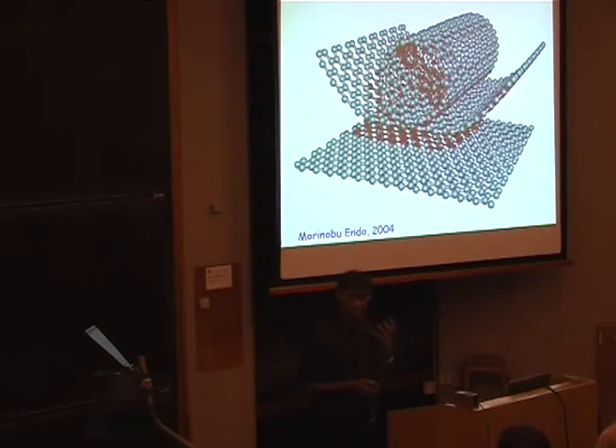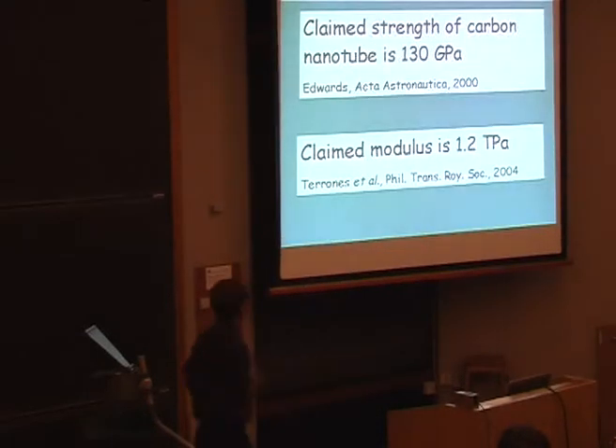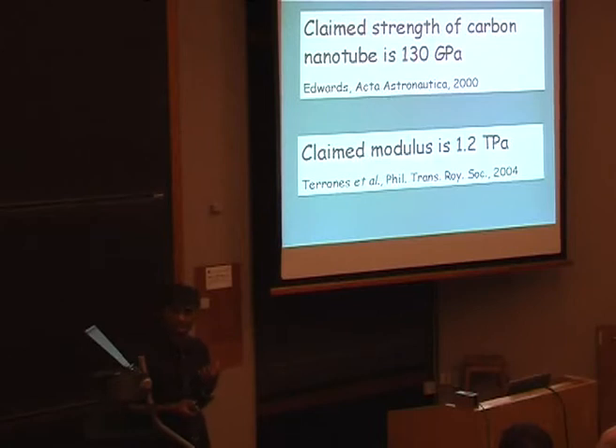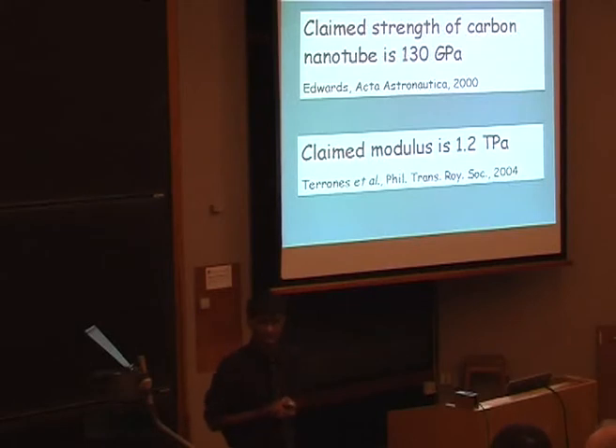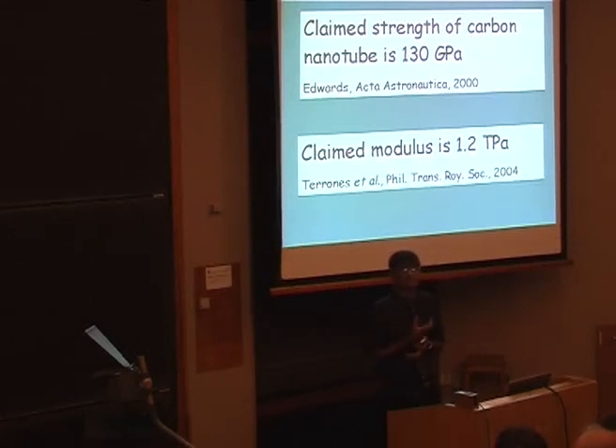And there are some extraordinary numbers that go with these carbon nanotubes. The strength, which is 130 gigapascals. This is strength beyond our dreams. And along the length, the modulus is 1.2 terapascals. It's extremely stiff. And these numbers are so astonishing that they have taken a sort of form of truth that almost everybody, including if you read the Philosophical Transactions of the Royal Society, will state this strength and then compare it against steel, as if steel is a homogeneous lump with unique properties which are constant. Okay. So I'm going to show you how we can beat carbon nanotubes in strength, 130 gigapascals.